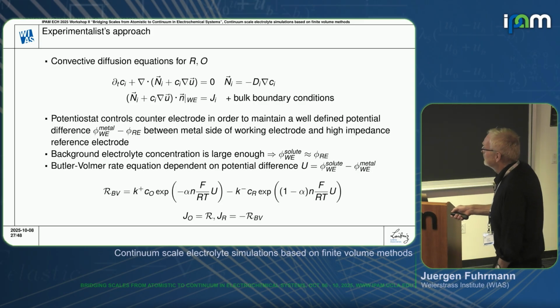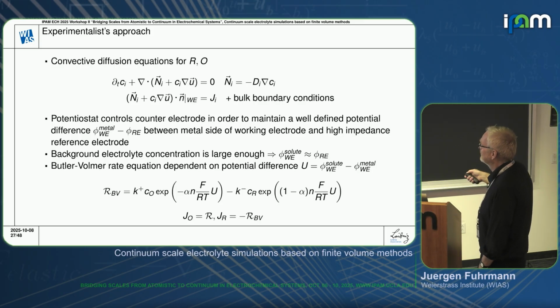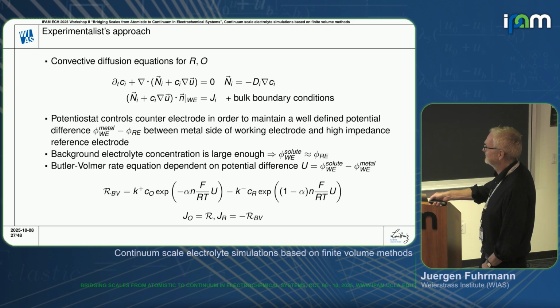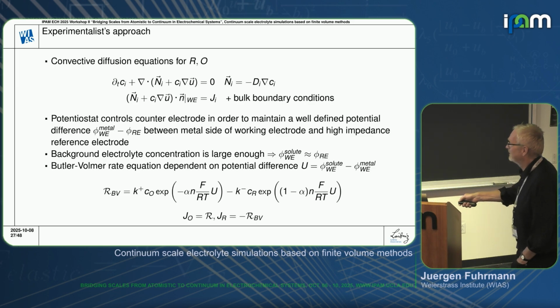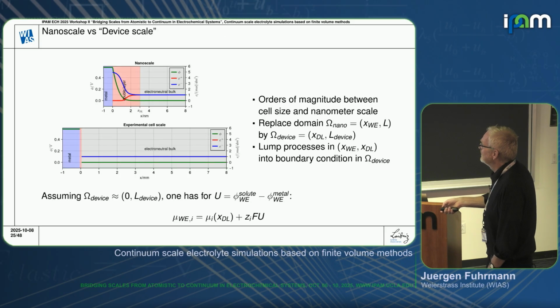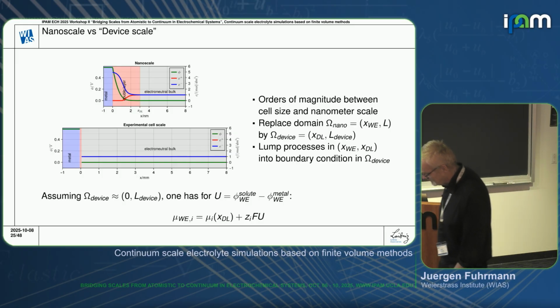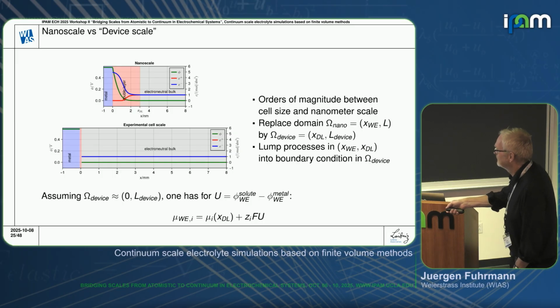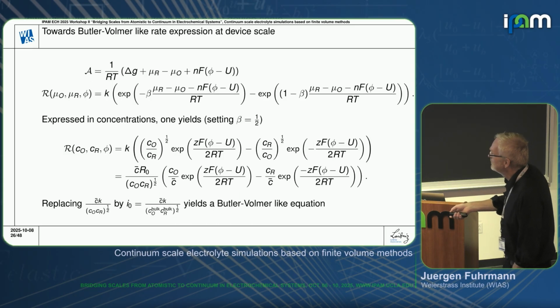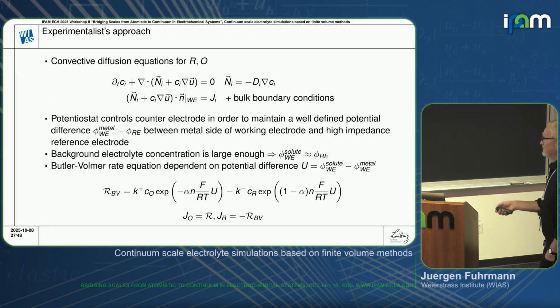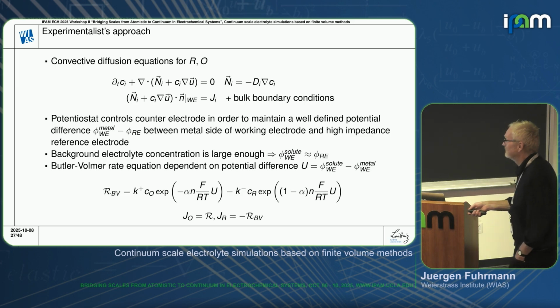The potentiostat controls the counter electrode in such a way that a well-defined potential between the metal side of the working electrode and some reference electrode is maintained, and the value of the potential in the reference electrode basically corresponds to the potential value in our electroneutral domain. With a well-supported electrolyte, you can place it close to the electrode and assume that it's constant, and we get this potential jump for our calculations. Then we get this Butler-Volmer rate equation.